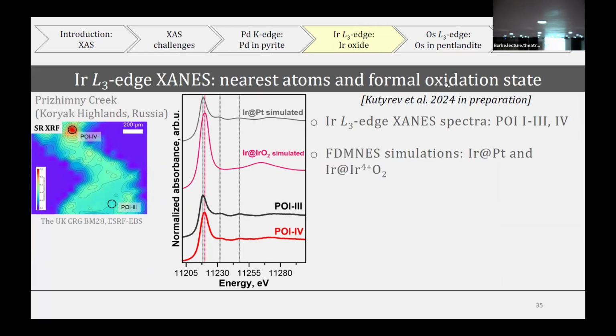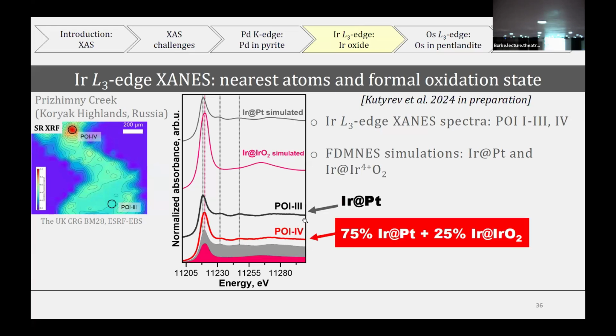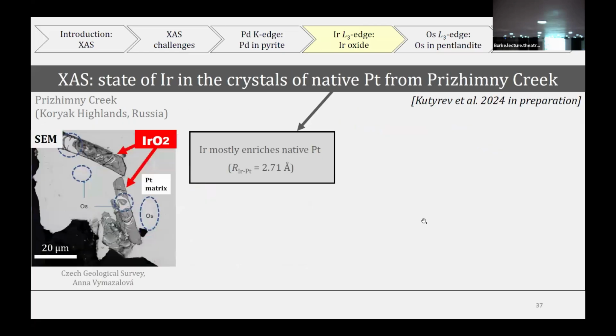Then we performed the FDMNES simulations, and here are 2 of them: iridium in platinum and iridium in iridium oxide. Through comparison with these standards, we realized that according to the XANES analysis, in most of the grain we have iridium in the platinum matrix, so it's a kind of intermetallic compound. But in this spot, we have up to 25% of iridium oxide. Why 25? Because our beam is about 40 to 60 microns here, and the inclusions were quite small, so we were covering the matrix around the inclusions. Yeah, and in general, for this system, let's sum up what we found out.